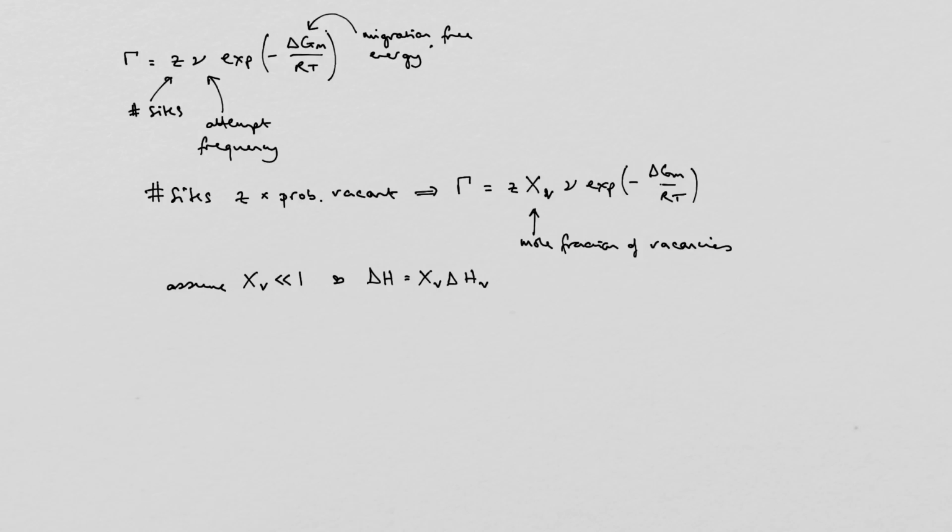That is a mole of vacancies that are so far away from the nearest other vacancy that there's no interaction between them elastically or in any other way. So if you like, this would be the way that you would calculate this. You're really asking yourself, if I just have a perfect crystal and I create a single vacancy in it, how much does that cost? And then multiply that by Avogadro's number. That would be the way that you do it.